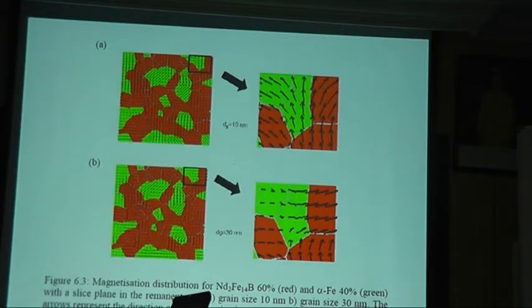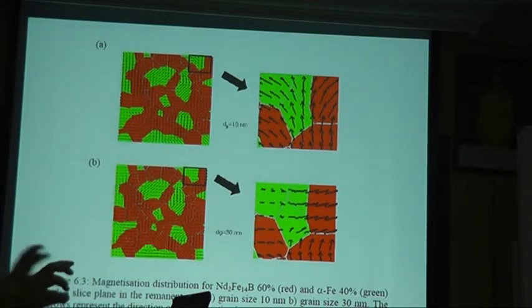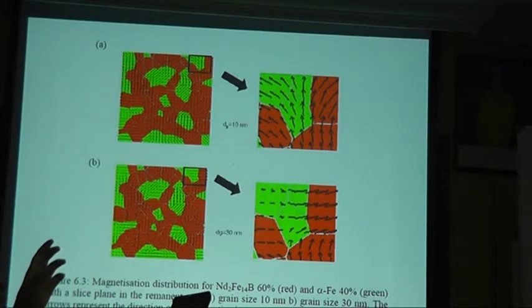The exchange coupling actually happens when we have two grains, soft and hard, in the distance, let's say for NdFeB around 4 nanometer. So the exchange energy tries to be minimum, and makes sure that the spins are arranged in parallel. Like this is soft, this is hard. But if the grain is bigger, 30 nanometer, in simulation 30 nanometer is still considered big.